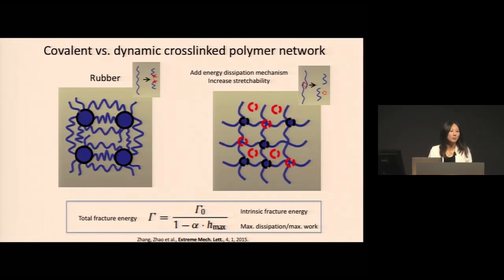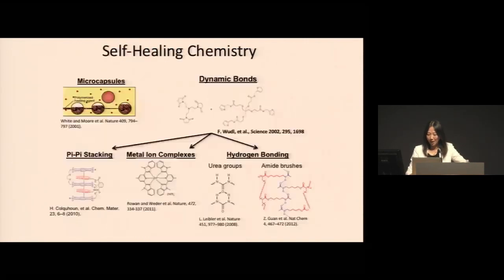But at room temperature, they can still recover and reform its original bond and allow the material to recover its original mechanical property. But the breakage of these bonds allows energy dissipation so that these materials can tolerate high strain and also have a very large fracture energy.